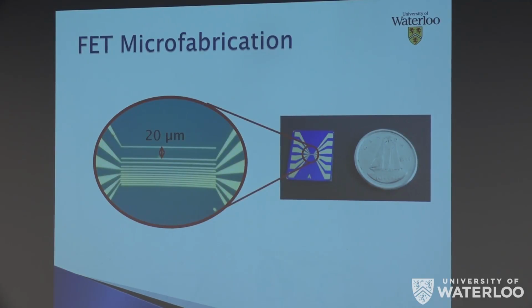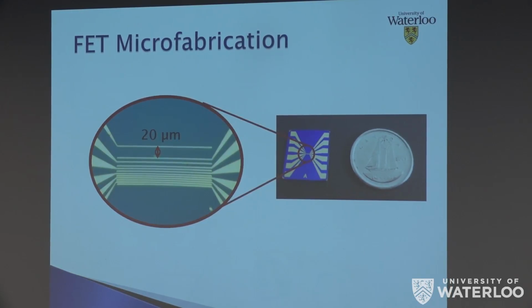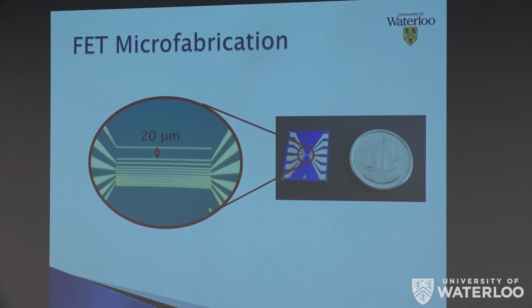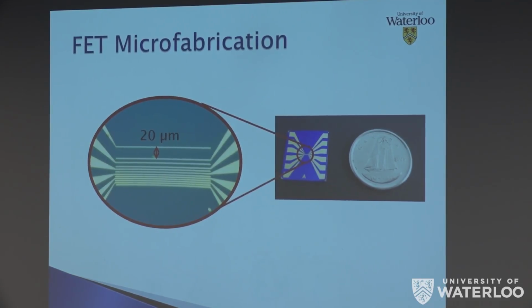These are the results of our microfabrication. You can see on the right-hand side our full device, which is smaller than the size of a dime. However, on the left, you can see an optical microscope picture of the active region, which has the largest feature size at about 20 micrometers. You can also see on the left-hand side that the electrodes aren't actually connected at this point, which is where the graphene will come in to complete the connection.